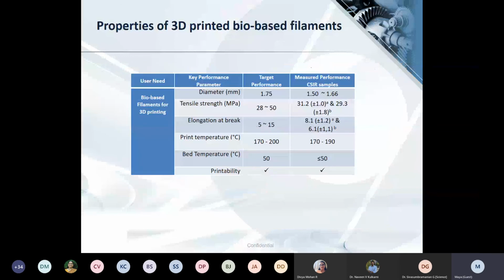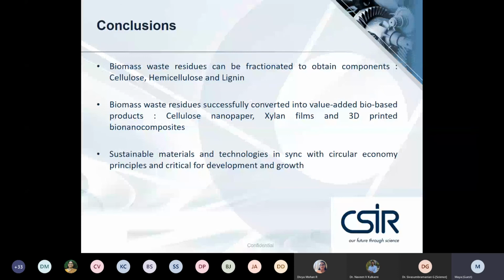And when we looked at the properties of the developed 3D printed bio-based filaments, it was found to be compatible with the natural fiber filament that's there in the market. An additional advantage was that we saw that the processing temperatures that we used were quite low when compared to that of the market. So some of the conclusions here are that the biomass waste residues can be fractionated to